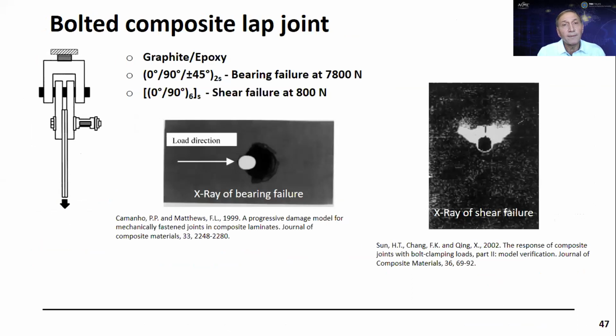My next example is bolted composite lap joints. So we considered these two studies published by Camanho and Sun. In one case, they have this quasi-isotropic laminate. In the other case, it's cross-ply. There are no 45-degree plies. And they observed bearing failure. And in the second one, because there are no plus minus 45s, there's a shear failure. So we went ahead and modeled this using Peridynamics.